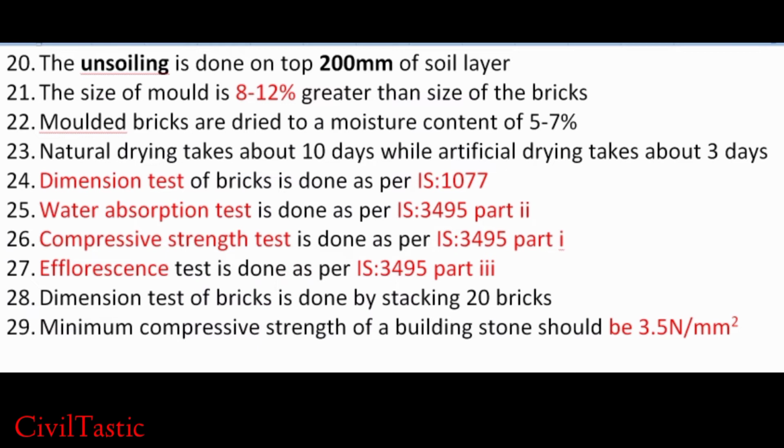Dimension test of brick is done as per IS 1077. Water absorption test is done as per IS 3495 part 2. Compressive strength test is done as per IS 3495 part 1. Efflorescence test is done as per IS 3495 part 3. Dimension test of bricks is done by stacking 20 bricks.